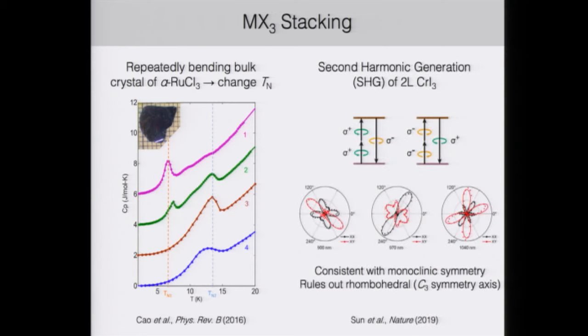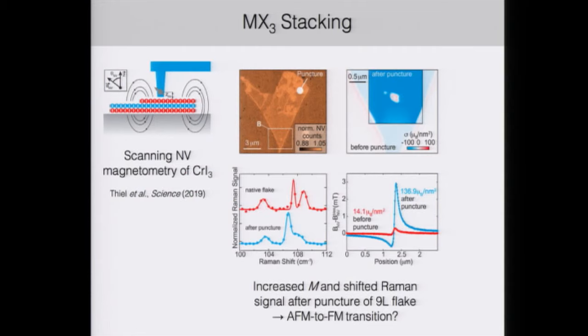There's also been some very nice work on second harmonic generation of bilayer chromium iodide at low temperatures, and the symmetry patterns that they observe are consistent with the monoclinic symmetry at low temperatures, and further also rule out rhombohedral symmetry, which would require a C3 symmetry axis and a threefold pattern in their signals. There's been more work on chromium iodide stacking.